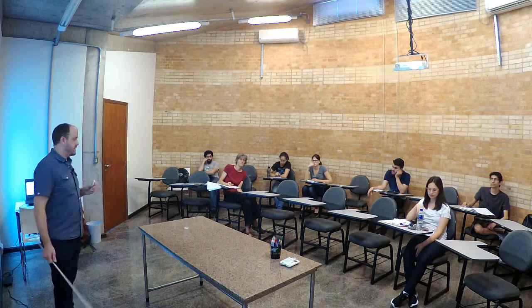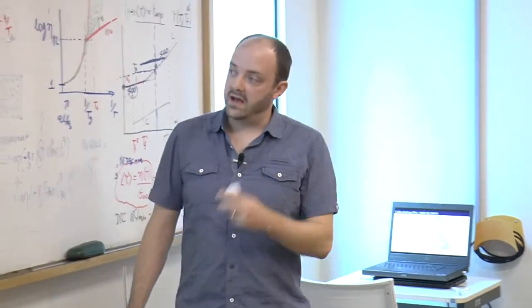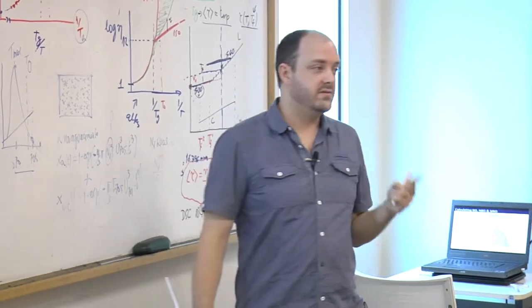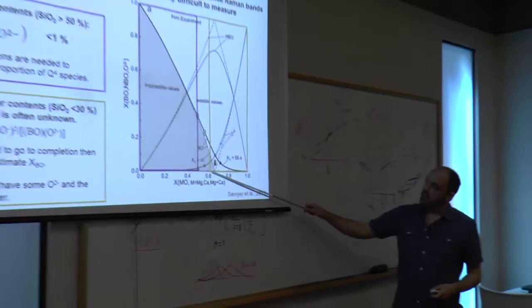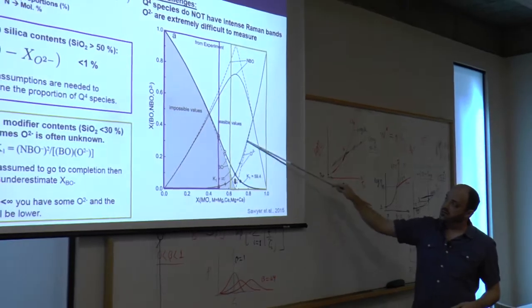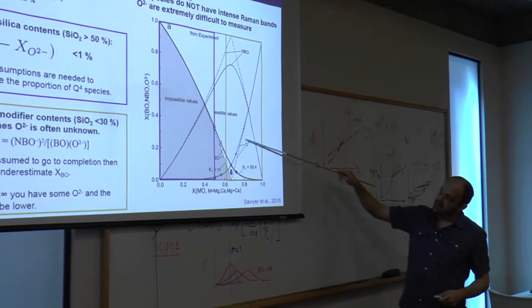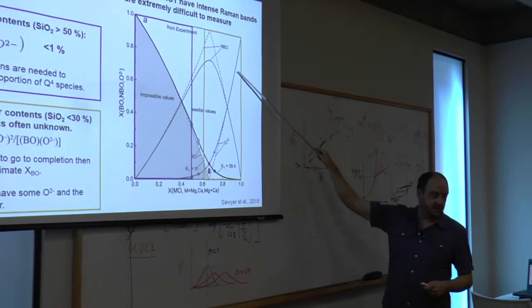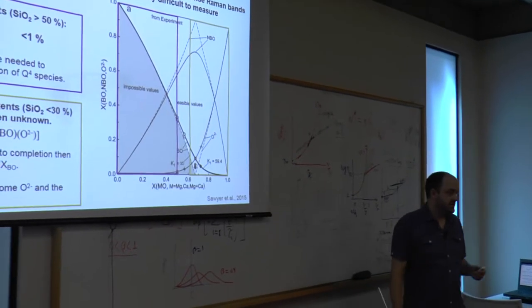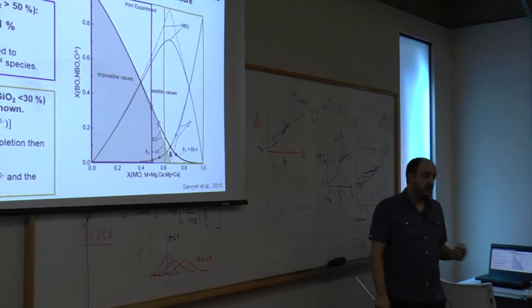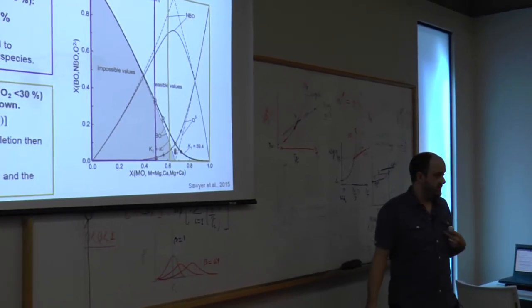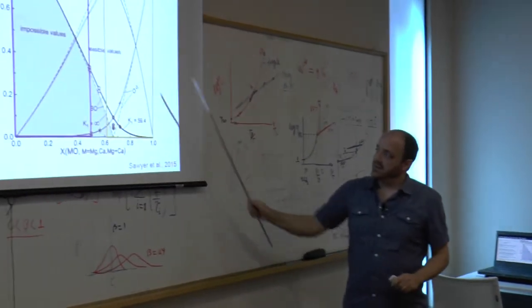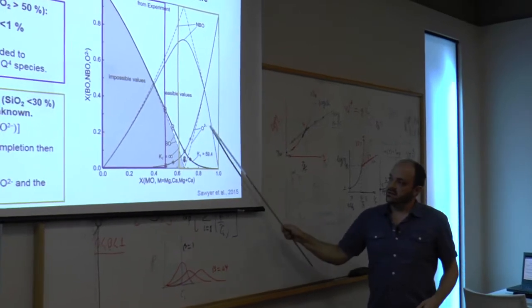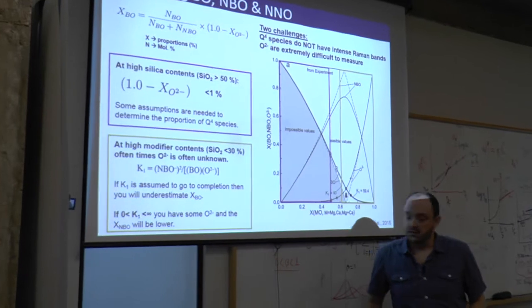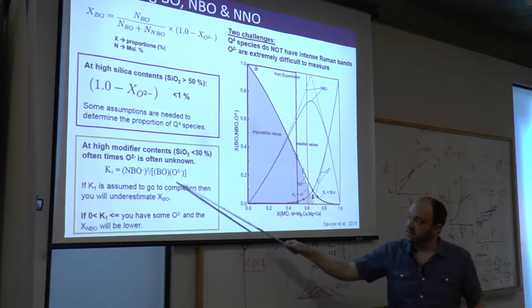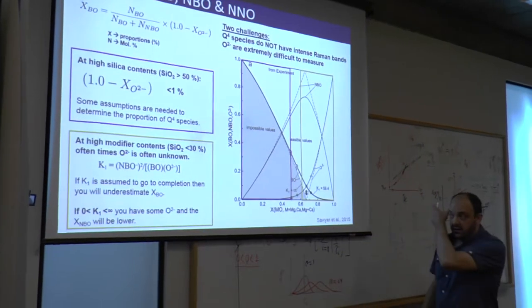So where we get into trouble with this conceptual model of adding modifier and converting bridging oxygen into non-bridging oxygen is twofold. First of all, when you have very low silica and high modifier contents, you have potentially, or not potentially, but most probably, very high amounts of this free oxygen or non-network oxygen in your glass. This is extremely difficult to measure. There's literally only a handful of studies that have measured the amount of this non-network oxygen in the literature, at least to my knowledge, of silicates, I should say. So it's very difficult to actually measure this. So you need some end-around to get at this information, and that's if you can figure out your rate constant here, then you can actually calculate this non-network oxygen from the proportion of bridging and non-bridging oxygen in the glass.